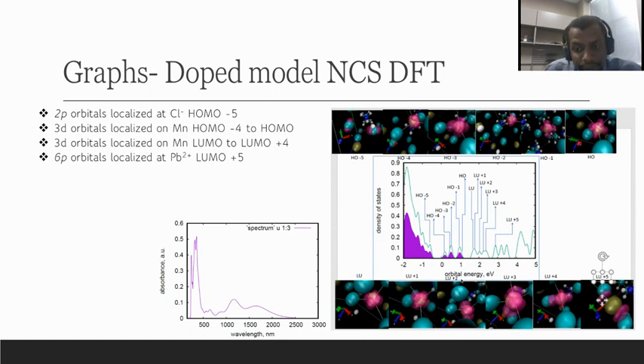So this result tells us that this non-collinear spin DFT, when accounting for the spin-orbit coupling, even though we didn't actually separate them, we have these alpha and beta orbitals both together. We can look at them and identify them, and this tells us that it's a good method to use as well to account for this phenomenon that's not supposed to be possible in the regular case. It's forbidden, right?